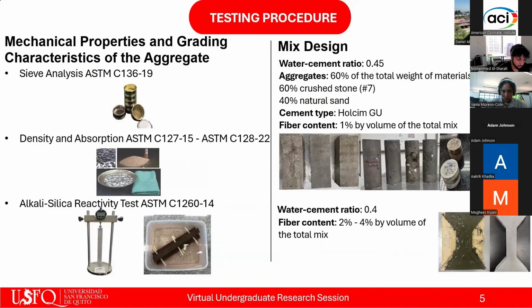Six mixes were produced, 3 with natural aggregates combined with synthetic and natural fibers, and 3 with recycled aggregates using the same fibers presented. From each batch, we cast 4 prisms, 20 inches by 6 inches by 6 inches, and 6 cylinders, 4-inch diameter by 8-inch height. 3 cylinders were tested in compression, and 1 was sliced into discs 1 inch thick for dynamic modulus testing.